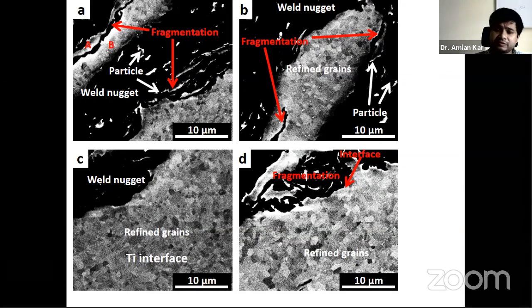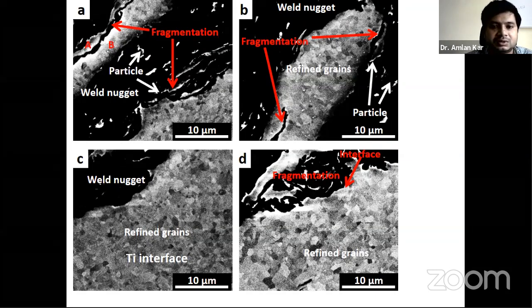This leads to the evolution of higher temperature, close to 700 to 1000 degrees centigrade, and that could possibly lead to recrystallization in titanium at the interface. But if the recrystallization has taken place due to the adiabatic shear band process, then we can expect similar features in particles as well, because this is an adiabatic shear deformation process. That means the shear deformation takes place only at certain locations, not at the gross level.